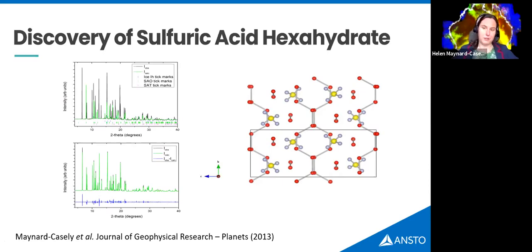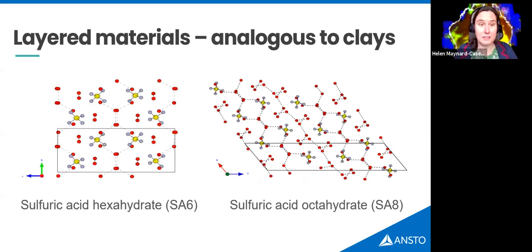This has probably been one of the reasons that people have struggled to pull out the spectral data, because probably whenever you're crystallizing octahydrate, you're also getting the hexahydrate as well. And one of the reasons behind this is actually how similar their crystal structures are. They both have the same layers all the way through them. So these water layers come through, and I've put dotted lines that show the hydrogen bonding through them. I always describe sulfuric acid octahydrate as a peanut butter sandwich, where the sulfate is like the peanut butter, and sulfuric acid hexahydrate as a peanut butter and jelly sandwich, where it actually has hydroniums within the structure as well.